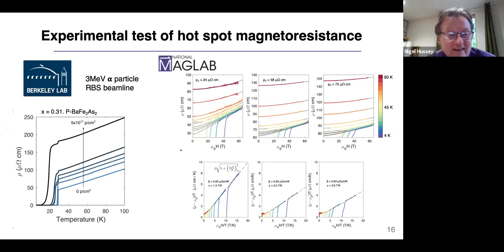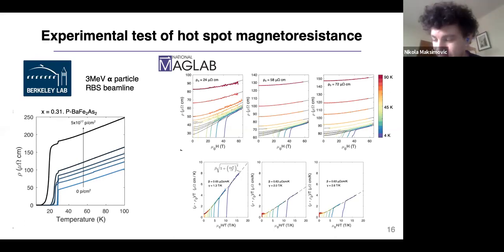So looking at this slide, clearly you have this sample with a residual resistivity well over 150 micro-ohm centimeters. It'd be very interesting to see how this evolves. Do you have at least preliminary data on that, or is the magnetoresistance just too small to resolve this kind of scaling? Unfortunately, we don't have data, because right about when we were putting this together is when the pandemic hit. So we were not able to measure these most disordered samples. That's something to do in the future.